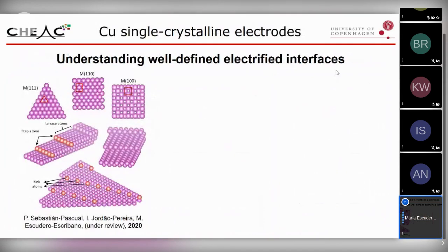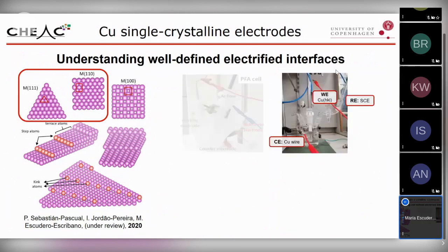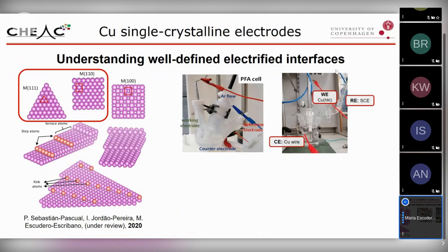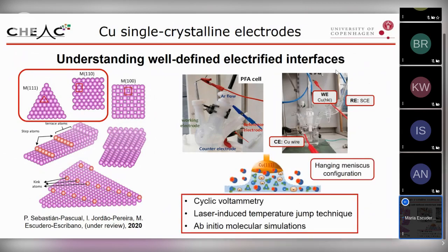And then the work I'm going to show is focused on single crystalline copper, copper 111 and copper 110 in different electrolytes. In the case of alkaline electrolyte, we use a PFA cell, and all the work was done in the hanging meniscus configuration. And what I'm going to present is a combination of cyclic voltammetry with the laser-induced temperature jump technique and molecular simulations. So for that, we have been collaborating with the Alicante group, Juan Feliu and Victor Climent, for the laser technique, and with Jan Rossmeisl at my department at the University of Copenhagen for the theoretical calculations.